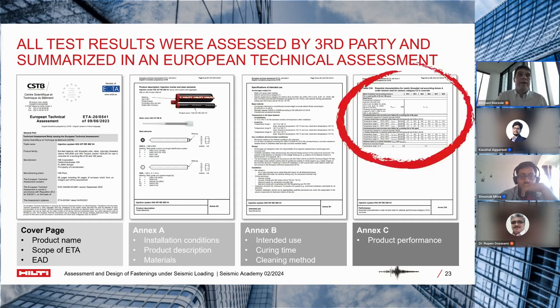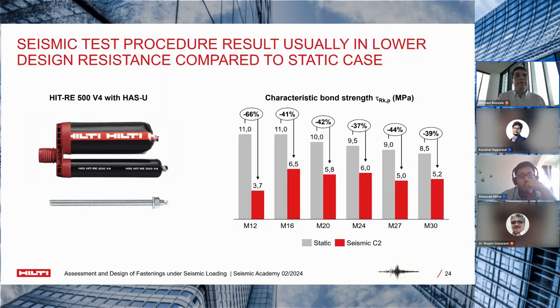And the last part, the annex C, shows basically the performance, all the product performances, and also, for example, for bonded anchor, the bond strengths that can be used under seismic conditions. And just to show you on the next slide how important it is, this chart on the right hand side shows basically the differences between the bond strengths that the specifiers can utilize under static conditions, that's the gray bar in cracked concrete. And for comparison, you see the red bars for the different sizes for seismic conditions. And there, these crack cycles and so on reduce the bond capacity, that's clear. And you see on average, it's about 50% of the performance, or you see a drop of up to 40, 50, 60% for the design under seismic loadings.